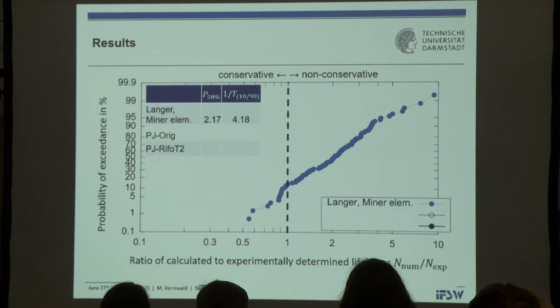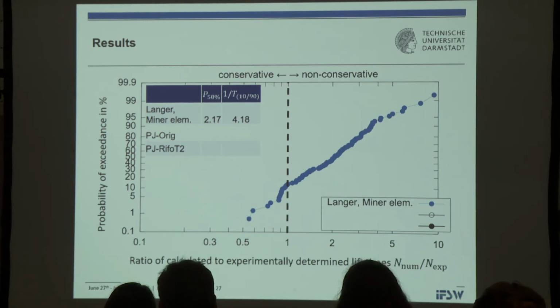And I start with the distribution of these ratios of calculated to experimentally determined lives. And again, if the numerically determined lives are larger than the experimental ones, then you are on the non-conservative side. And Langer and Miner means this is the approach which is laid down in German rules on how to calculate variable amplitude life, as far as they told us. And this is, on average, on the unsafe side. So the mean value is 2.17, and this is our German scatter value.